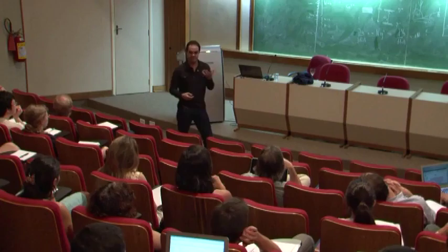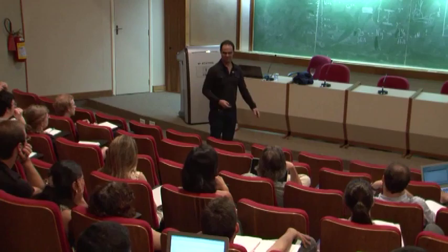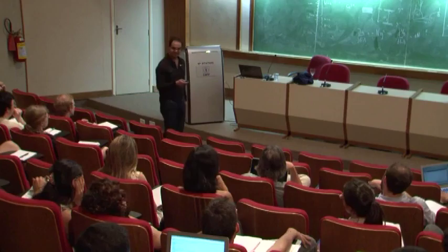Right. So assume that I want to grow a phase that has a lot of plutonium, more plutonium than indium, but I want to add cobalt. And then I look at the cobalt-indium diagram and the plutonium-cobalt diagram. And then I look at the temperatures and the ratios. And then I say, well, okay, I need like 3 plutonium per indium, and how much cobalt to plutonium, and how about the temperature? So you try to construct that. Sometimes it works, sometimes it doesn't work. That sounds very tedious. It is.